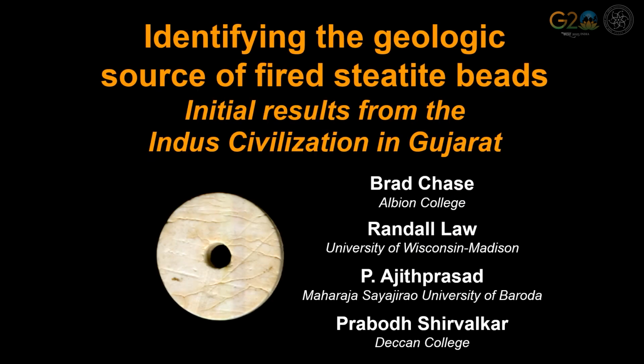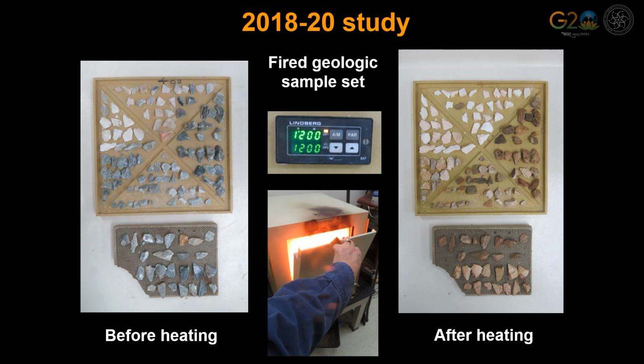Nevertheless, in recent years, I have been collaborating with Dr. Brad Chase of Albion College in an attempt to determine the geologic sources of steatite beads. For this new study, we first had to heat treat a set of geologic samples in order to make them directly comparable to fired steatite beads. In addition, the neutron activation analysis parameters had to be adjusted to accommodate the small sample size that is typical of such beads.